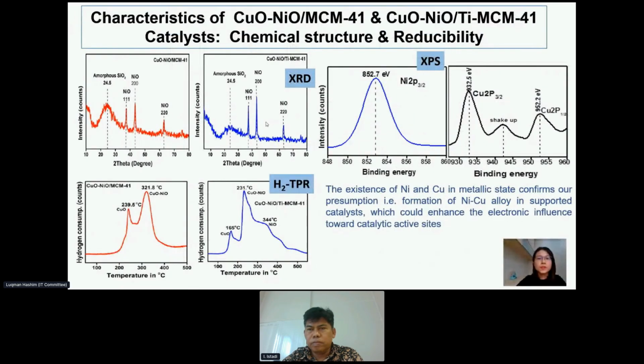Now we will discuss the final catalyst, which is the bimetallic copper nickel oxide that is supported with the MCM41 or modified MCM41, based on the chemical structures and the reducibility properties. So based on the XRD analysis, it is found that the copper oxide species for both samples could not be observed, which is due to the small particle size of the copper species, and this resulted in better dispersion within the mesoporous support, either the modified and unmodified mesoporous support.